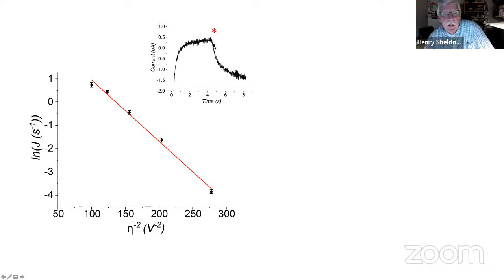And once you're out of the noise, see where my pointer is? If I say I'm out of the noise here, or it's disappeared, at that point the particle has grown from 1 or 2 atoms up to about 1 nanometer in size, thousands of atoms. It's really fast. I mean, look at the time scale. This is seconds. So electrodeposition on 100 nanometer scale is just incredibly fast. Got it.